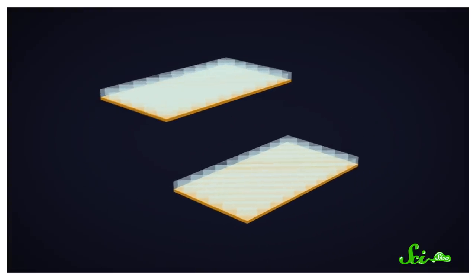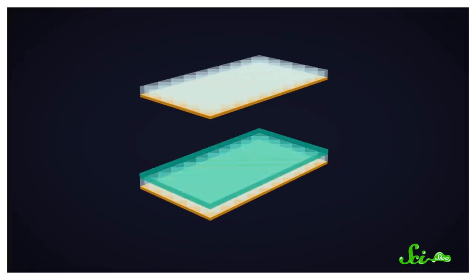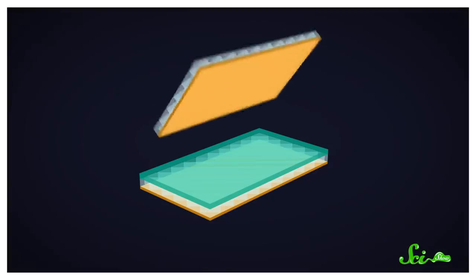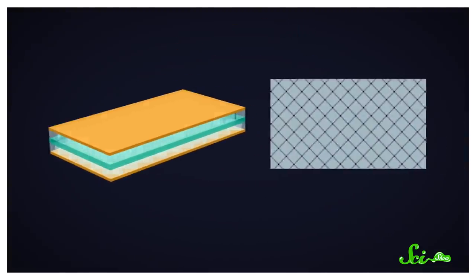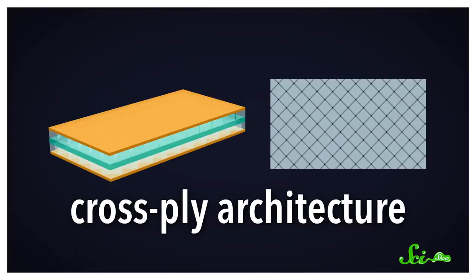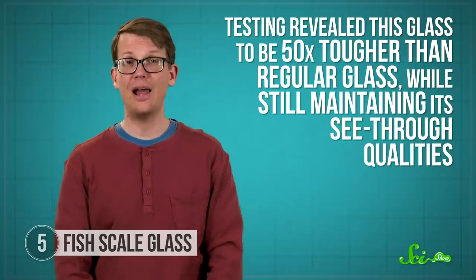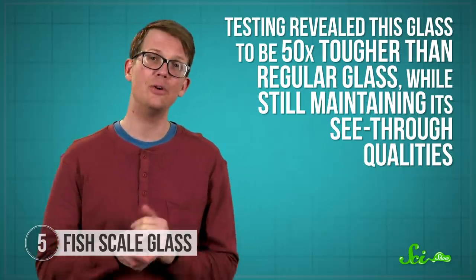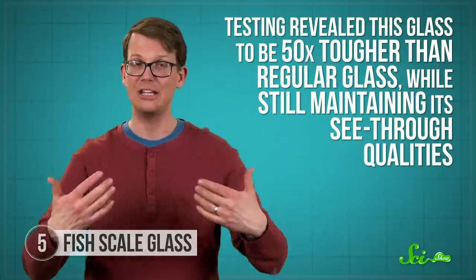Then they laid the sheets of glass on top of each other with another layer of flexible polymer sandwiched between. They also rotated the top sheet of glass so the etched lines go in the opposite direction, known as cross-ply architecture, and that gives the glass added strength and flexibility. When this type of glass is stressed, the cross-ply architecture and stretchy polymer middle work together to help the glass be stretchy and tough instead of brittle. Testing revealed this glass to be 50 times tougher than regular glass while still maintaining its see-through qualities. If this kind of glass spread, that would mean stronger, safer windows that might need to be replaced less often, all thanks to a pattern inspired by fish.